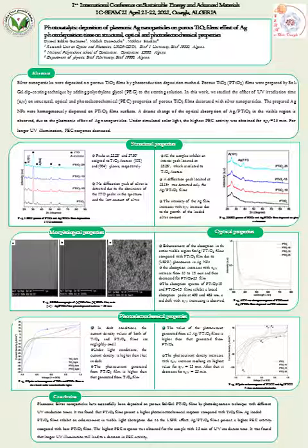Figure 5 presents cyclic voltammograms of TiO2 films prepared with and without PEG. Under simulated solar light, the generated photocurrent from porous TiO2 film with PEG is greater than that generated from TiO2 film without PEG, which is due to its higher specific surface area.